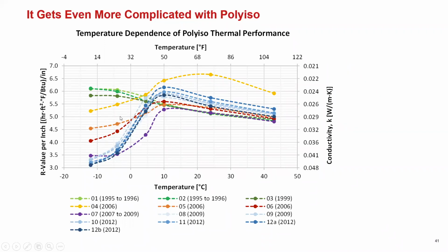And just to look at the outlier, the polyisocyanurate, there was a consulting firm, RDH Building Science Labs, Dr. John Straub and his team wanted to do some research on the polyiso, this phenomenon of reduced R value. And what they noticed were that there was a series of products from manufacturers back in the mid-90s that would increase in R value at lower temperatures, but that trend stopped shortly thereafter, and now we're starting to see this drop. And so they were able to align it with the Montreal Protocol, and recognizing that there was a lot of blowing agents that were being banned for use in construction and other applications because of their impact on depleting the ozone layer. So as a result, they had to change their cocktail a bit. And the gases that they're using now have a tendency to condense at roughly 50 degrees Fahrenheit and become more conductive. And so that's why you're starting to see a drop in that R value at lower temperatures.